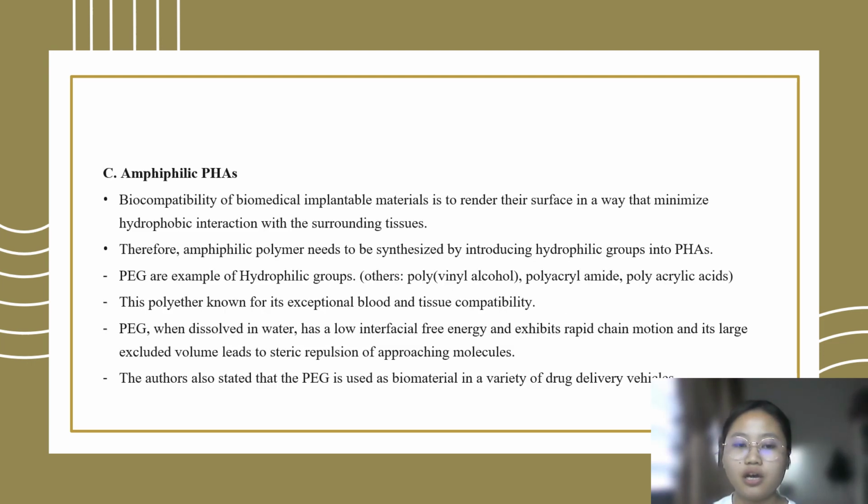Next is amphiphilic PHA. Biocompatibility of biomedical implantable material is to render the surface in a way that minimizes hydrophobic interaction with the surrounding tissue. So therefore, the amphiphilic polymer needs to be synthesized by introducing hydrophilic groups into PHA. PEG is an example of a hydrophilic group, which is a non-ionic polyether with exceptional blood and tissue compatibility. PEG, when dissolved in water, has a low interfacial free energy and can exhibit rapid chain motion, and its large excluded volume leads to steric repulsion of approaching molecules. So the author also stated that PEG is used as a biomaterial in a variety of drug delivery vehicles.